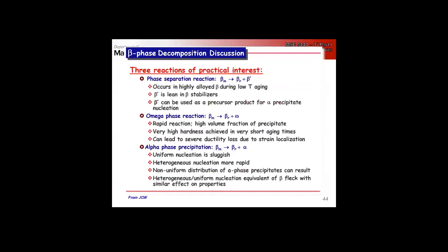So that means we're going to want to take advantage of nucleation at dislocations, subgrain boundaries, right? Take advantage of omega to alpha and beta prime to alpha, right? Because we want to avoid the non-uniform distribution of alpha phase precipitates.